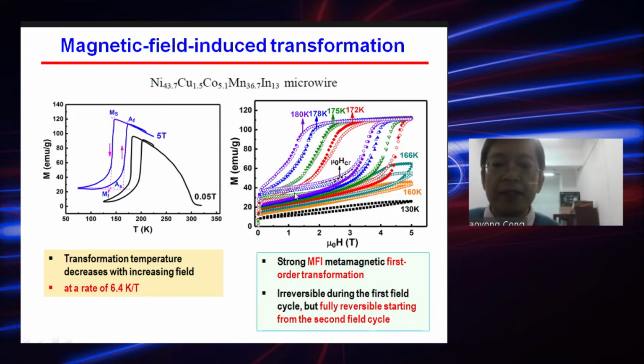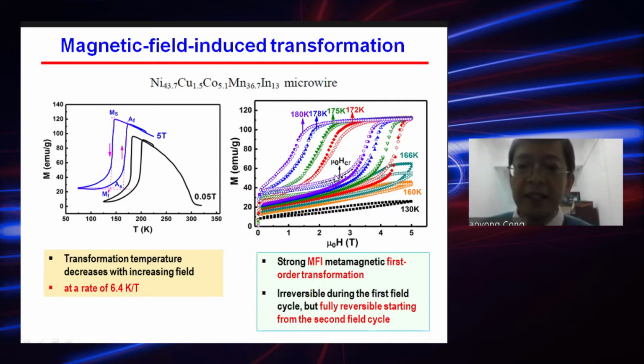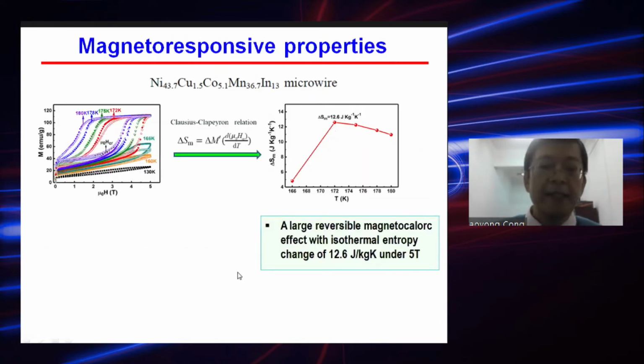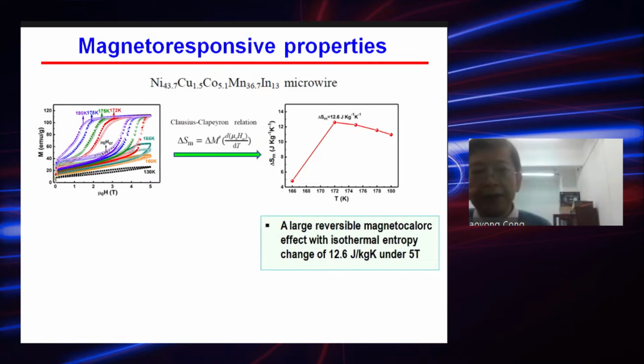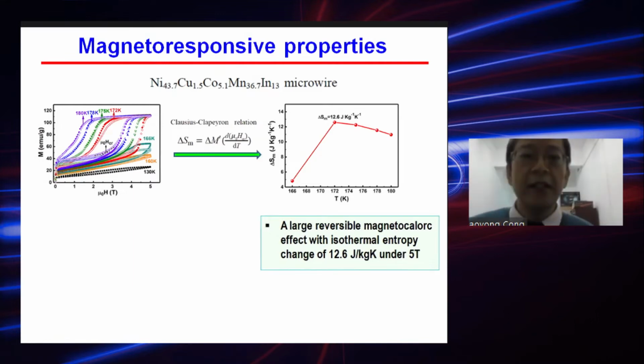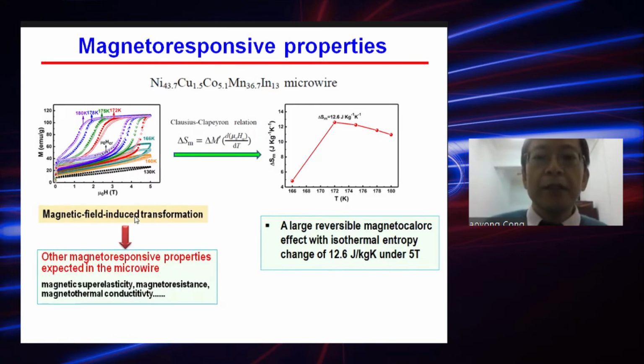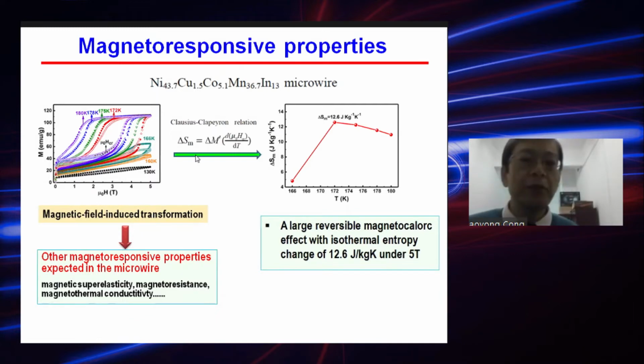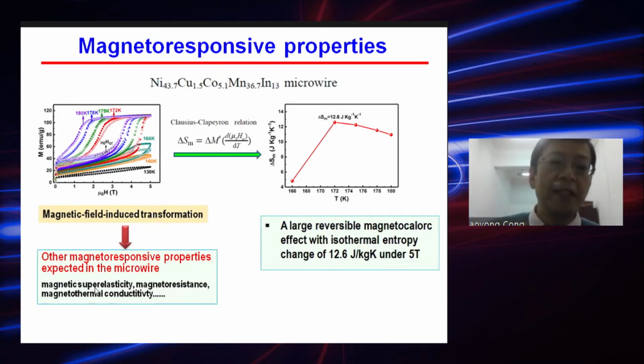Although this transition is somewhat irreversible during the first cycle, starting from the second cycle, it becomes fully reversible. This reversible magnetic field-induced phase transition can give rise to a variety of magneto-responsive properties. For example, magnetocaloric effect, magnetic superelasticity, magnetoresistance, and magnetothermal conductivity.